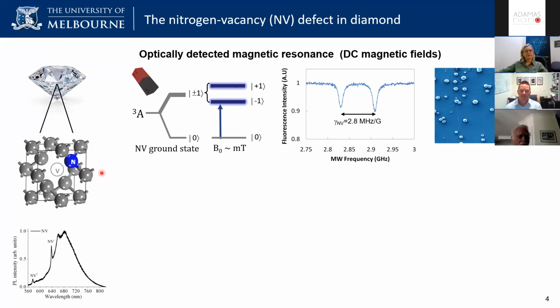And so the NV center, the negatively charged NV center, has some really unique properties that allow things like ODMR to be done. The first unique property is the fact that if we shine green light onto these materials, we can polarize the electron spin into the m_s = 0 state. And this is one of the really unique features of diamond and the NV center in particular. So we get spin polarization for free, if you like, by just shining green light onto this system. We can then manipulate the electron spin between these ground state spin levels. So we can manipulate the spin from the m_s = 0 to the +1 or the -1 state, simply by applying a microwave field at the appropriate frequency, which is the energy difference between these 2 levels, which is typically 2.87 gigahertz.